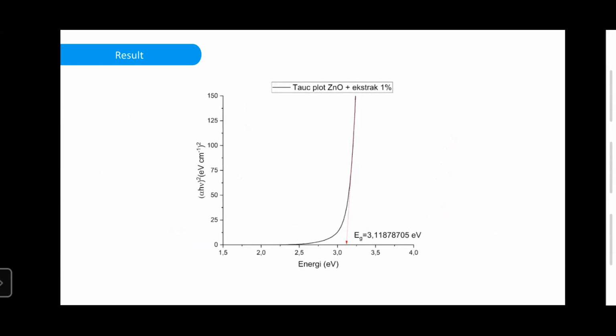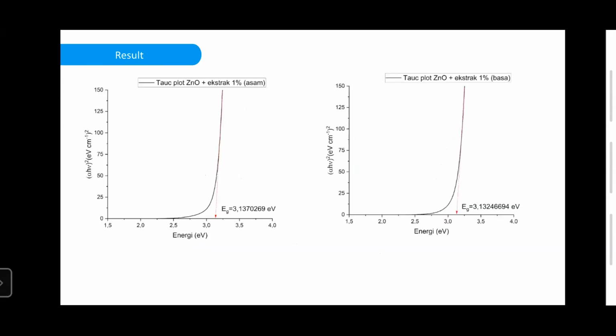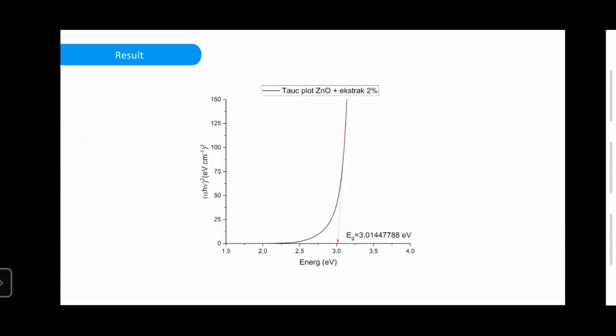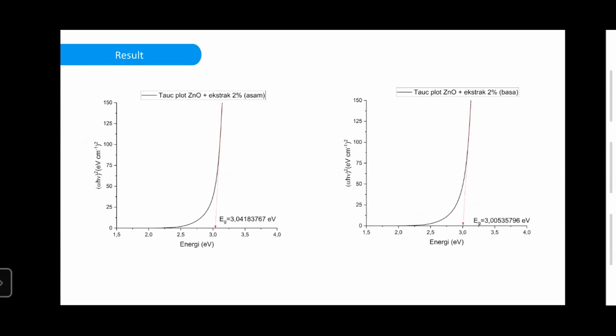Okay, and this is for 1% extract. I have 3.11 electron volt as energy gap. And then for the acidic solution, I have an energy gap of 3.13 electron volt. And for the addition of basic solution, I have 3.13 electron volt. And the last one is for 2% extract. I have 3.01 electron volt as energy gap. And then for the addition of acidic solution, I have 3.04 electron volt, and for the addition of basic it is 3.00 electron volt.